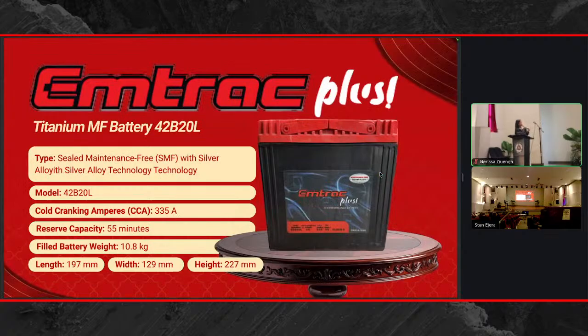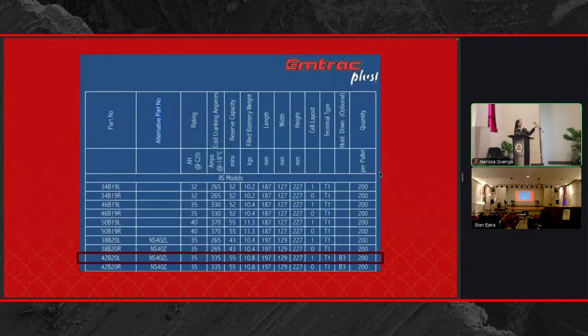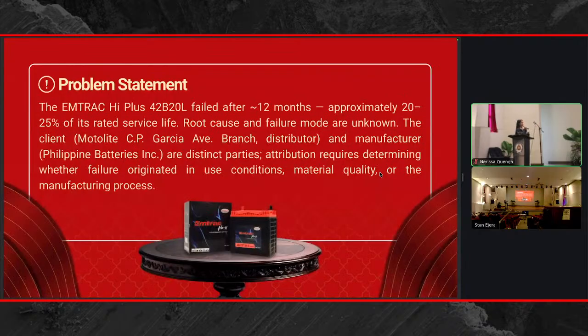So EMTRAC Plus is a sealed, maintenance-free battery with silver alloy technology. The model is 42B20L, and the cold cranking amperes is 335 amperes based on the specification sheet. And these are the other details. So here is the specification sheet. And for our problem statement, the EMTRAC Hi Plus battery failed after 12 months, approximately 20 to 25% of its rated service life, and the root cause and failure mode are unknown. The client, which is the Motolite at the CP Garcia branch, distributor and manufacturer, the Philippine Batteries Incorporated, are distinct parties. Attribution requirement determines whether the failure originated in use conditions, material quality, or the manufacturing process.